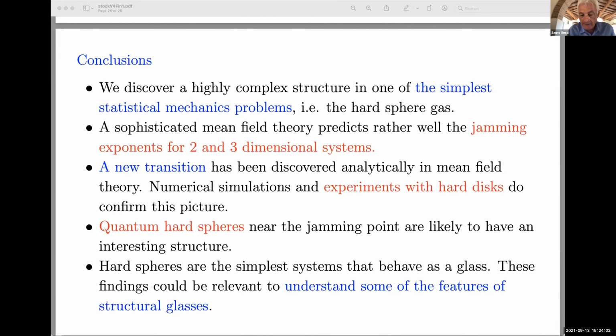First of all, I didn't know that you seem to get very good results as soon as you take into account this Gardner transition, as soon as D is greater than 2. Did I understand correctly? Greater or equal than 2. Okay. At 2, there may be a few percent difference between the exponent, but which may show up as logarithmic corrections. Okay, so it seems to me that this is a huge improvement, because the folklore was that mean field theory does not work other than in infinite dimension. This is no longer true. No, I mean mean field theory.